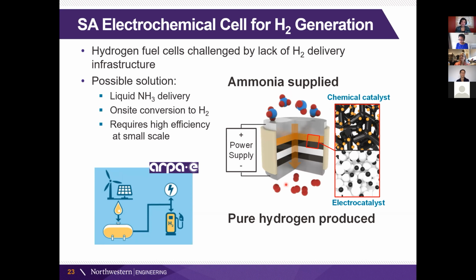And the advantage here also is that you can do electrochemical pumping so that you can create high pressure hydrogen that you would be putting into a tank, again, to put it into a hydrogen fuel cell vehicle. And so we're doing a design here then that's very similar to what I showed you for our direct methanol fuel cells, which is to combine some sort of chemical catalyst with our electrocatalyst layer. And this also gets around what I told you was our cathode is kind of lousy. In this case, we don't need it here because what we'll be doing is evolving hydrogen because we're not doing the fuel cell step, we're doing the ammonia to hydrogen conversion step.